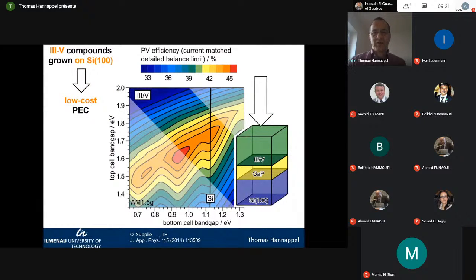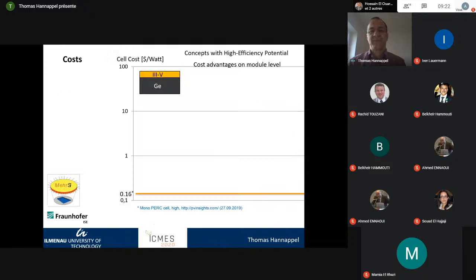Yeah, as I told, we need certain bandgap combinations, and what you can see here is the bandgap of silicon in the range of 1.1 eV. And if you would like to combine this to an efficient device, what you can see here is the combination with a top cell in the range of, for example, 1.7 or 1.8 eV, then we are here very close to the highest efficiencies of the bull's eye, and this also could promise for a device which would be competitive in terms of costs if we would use the workhorse of the semiconductor industry, the silicon, and upgrade it with a very thin layer of III-V semiconductors, for example. And this should be indicated here on this slide.